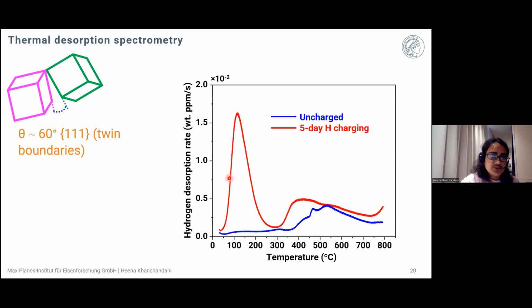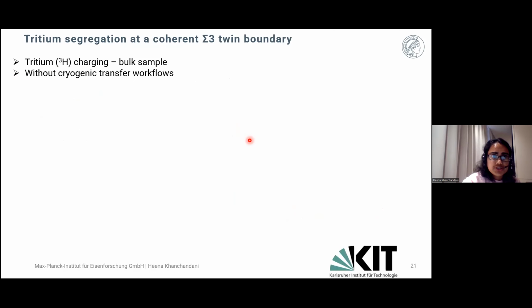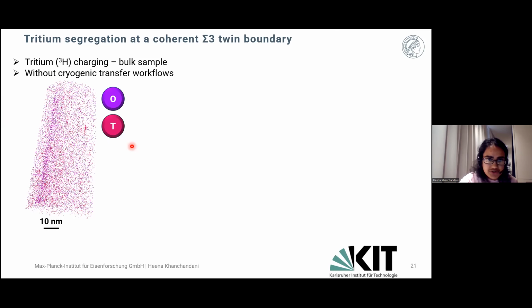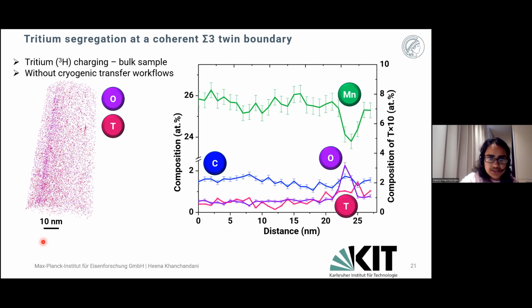Secondly, we performed a thermal desorption spectroscopy analysis, which showed that we really need to heat to very high temperatures in order to dissolve hydrogen out of the material. So this motivated us to perform these experiments on bulk samples without using any cryogenic transfer workflows. For this, we sent the samples for tritium charging to our collaborators in Karlsruhe. We sent them bulk samples, which were charged with tritium, a radioactive isotope of hydrogen. And then they were shipped back to Düsseldorf, where we did the lift-out and analysis. So they were not quenched, and there was a time difference of about 4 weeks between the charging and atom probe analysis. And we still observed the segregation of tritium and oxygen at the coherent sigma-3 twin boundary.